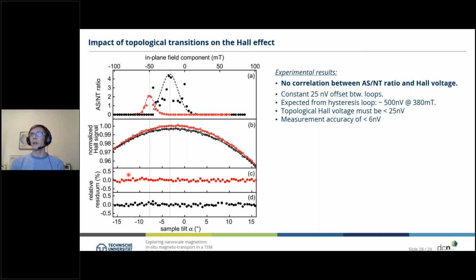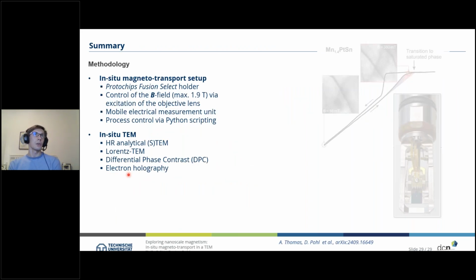So to sum up, there is no correlation between the anti-skyrmion non-topological ratio and the Hall voltage. We have an offset of 25 nanovolts between the forward and backward direction, which seems to be stemming from an additional magnetic texture which appeared during the tilt. The expected 500 nanovolts, which we found in the hysteresis loop, cannot be explained by a topological Hall effect. In our case, the topological Hall effect must be smaller than 25 nanovolts, with our measurement accuracy lower than 6 nanovolts. With this, I want to sum up my talk.